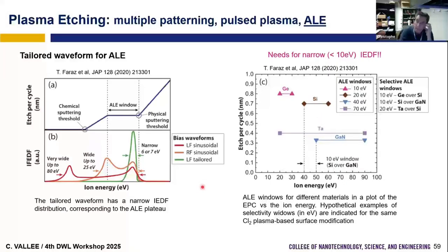So it means that it's very challenging, and we have to think about the bias waveform we use for directional ALE, because, for example, for most of the waveforms I've shown you, we don't have a narrow distribution. We have a more or less large distribution, and remember, it depends on the ratio between the frequency of the generator and the ion plasma frequency. So here you need a very narrow distribution if you want to perfectly etch silicon versus gallium nitride with the ALE process.